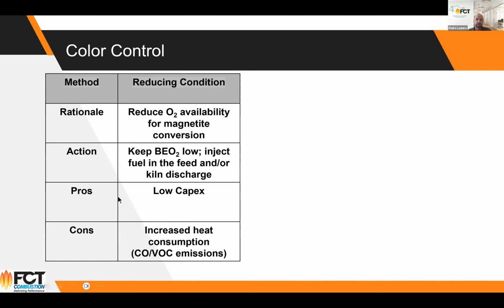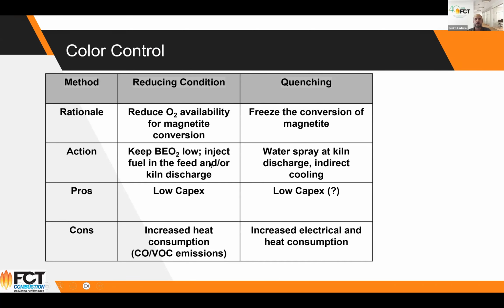The good thing, or the pros, of doing this is relatively low capex, but the cons is, depending on where you inject the fuel, you might have an increased heat consumption and VOC and CO emissions. And treating those emissions can be very, very expensive. Although the capex for injecting is low, the capex for controlling emissions can be fairly high. So this is the traditional way. An alternative way is quenching.